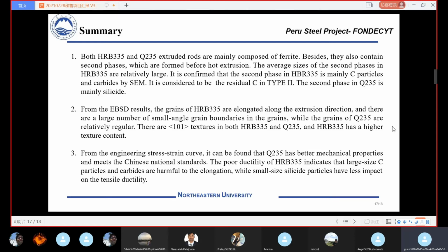And from the EBSD results, the grains of the HRB335 are elongated along the extrusion direction, and there are a large number of small angle grain boundaries in the grains. While the grains of the Q235 are relatively regular, there are <101> textures in both HRB335 and Q235, and the HRB335 has a higher texture content.